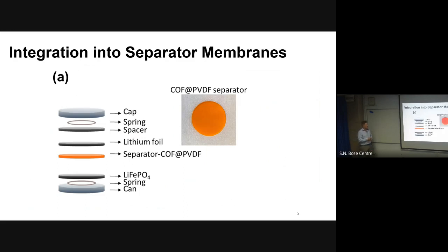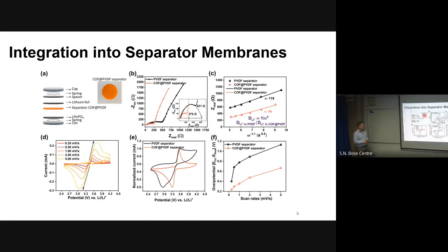We used a very simple setup. Here we have the top, the PVDF separator. We use lithium foil and lithium iron phosphate as the cathode material, and we use a carbonate-based electrolyte, so the LiPF6.